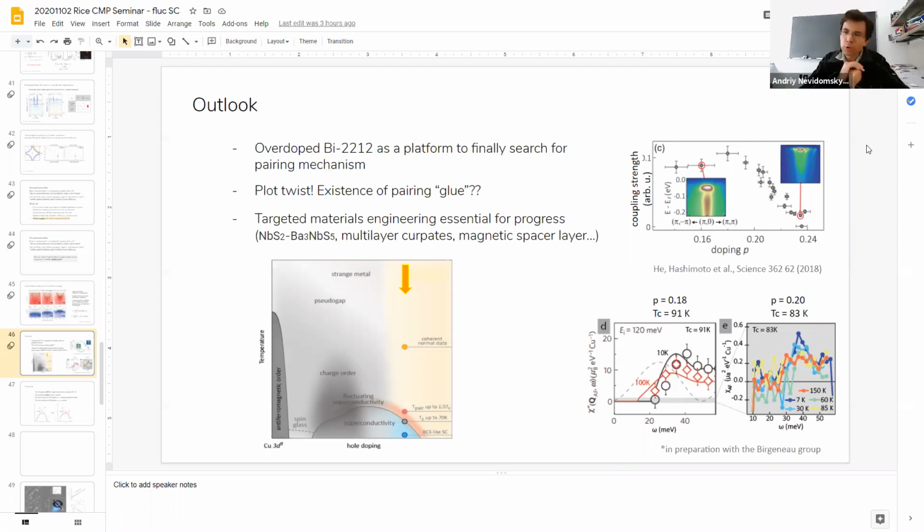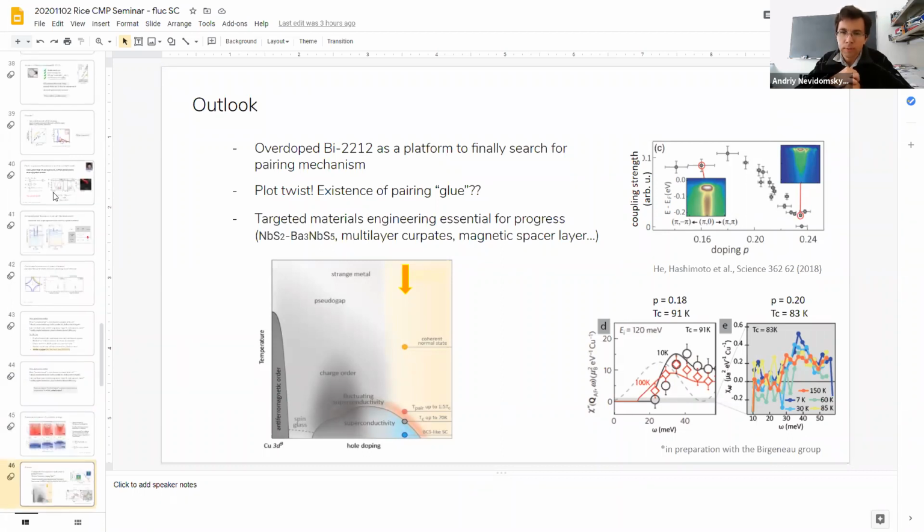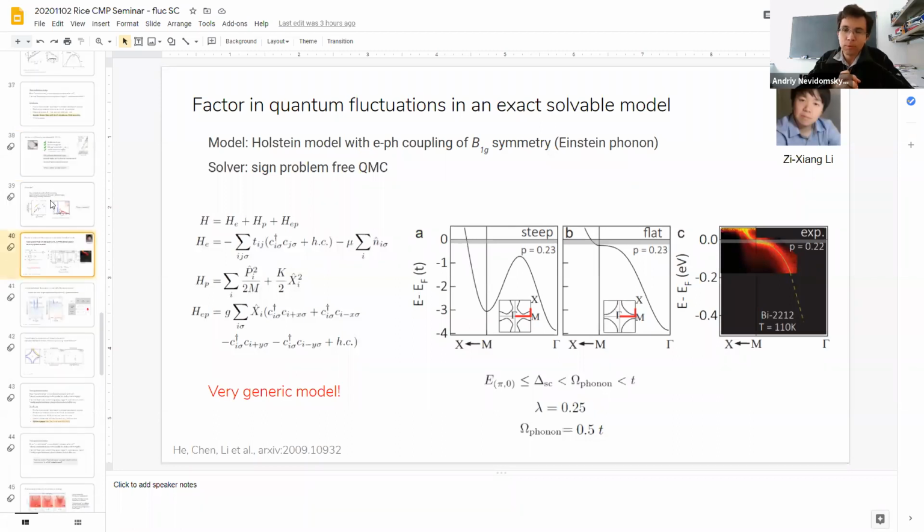I see. And if I may just, a very quick follow-up. So the nature of the fluctuating superconductivity you've explained very nicely and showed proof from different experiments. How am I to tie this up with the ARPES signature of that nearly flat band that you see near the M point? That, I guess, is the part that I missed. Yeah, that's the part I skipped. But just to give you an idea, there are materials like iron selenide, which you believe to be even closer to the BEC limit, where EF is tiny. For all purposes, you could say my EF is less than 10 milli-electron volts. And yet the fact that you have a very small EF doesn't mean that superconductivity has to be strongly fluctuating. So where is the connection?